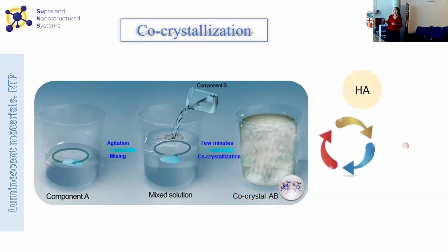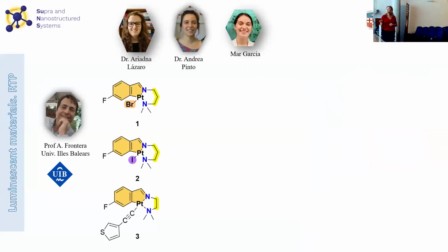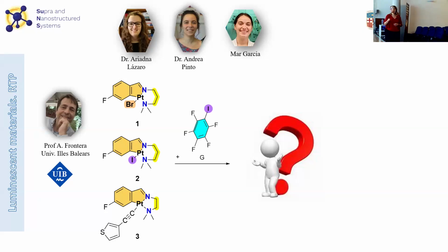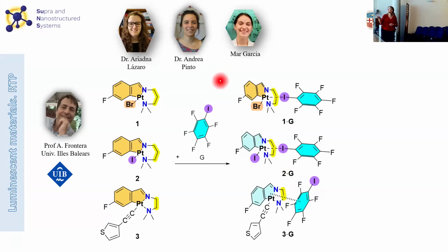But what we wanted to correlate is the effect of the heavy atom and the intersystem crossing on the resulting luminescent properties. This was an idea suggested, again, by our collaborator in the Balearic Islands, Tony Frontera, since they have expertise in this field. So what we did was react 3 of our compounds with a guest, the iodopentafluorophenyl, and see what happens. We don't know how the compounds can self-assemble, or if they react or not. Thanks to X-ray crystal diffraction, we could know that the first 2 compounds have a direct platinum-iodine bond, a weak bond interaction in both cases, while in the 3rd compound there is just pi-pi stacking between the platinum compound and the guest. So there are some clear differences in the resulting packing.